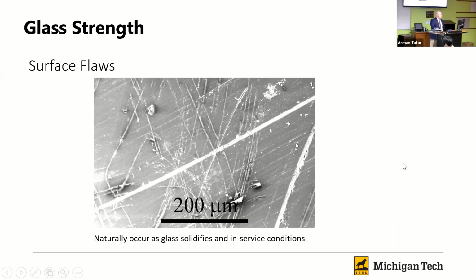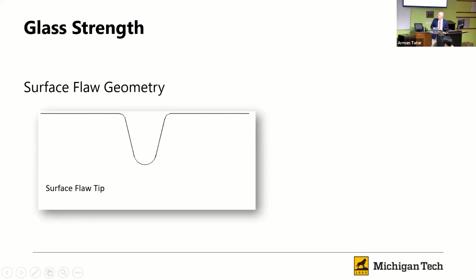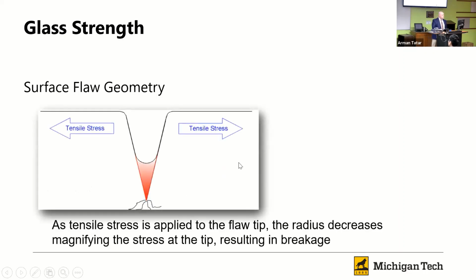But basically we have these little flaws, and what goes on with these flaws, we kind of model this as a side view. So we've kind of zoomed in and we're looking kind of through the thickness of the glass. Then we're going to have this little flaw here. And if we provide some tensile stress, what that's going to do is tend to sharpen the tip of that flaw. And if we create enough tensile stress and we get that flaw sharp enough, then we're going to have a large stress concentration, many times over what the original tensile stress was, to the point to where we create fracture, okay?